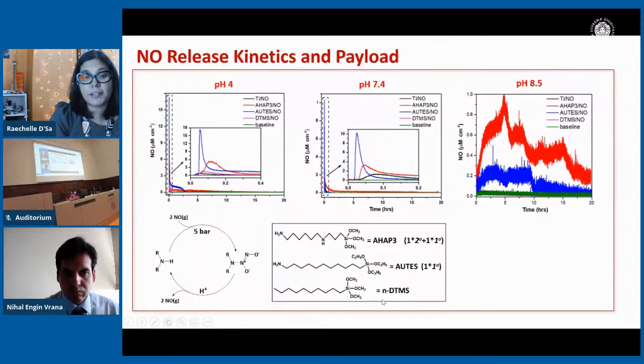And the DTMS, which has no capability of binding nitric oxide, you can see has a negligible amount of nitric oxide, which is just physisorbed. Titanium is the other surface in there, and you can also see that there's no nitric oxide or just physisorbed nitric oxide adhered onto the surface. When we look at the surfaces at pH 7.4, which is physiological pH, it follows a similar trend. The AHAP surfaces release slower than the AUTES surfaces, and you see some physisorbed nitric oxide on the DTMS surfaces. And when you move to pH 8.5, what you also notice is that the release profiles are once again longer because of the higher pH.